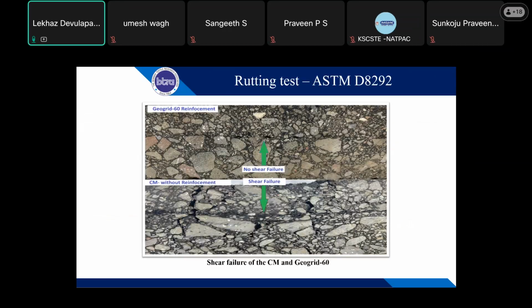And this is the cross section of a specimen. You can see here there was no shear failure. When it comes to this one, we have depressions and a lot of cracks formed on the bottom layer and also on the top layer. So when you have a geogrid reinforcement in the asphalt layer, it will resist the rutting, and shear failure may not happen that quickly, even after 20,000 cycles. The pavement also cracks prematurely, before the rut slope we calculate, for this unreinforced section.